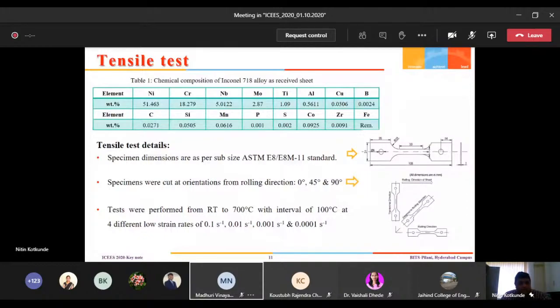It will take around 1 or 2 months of continuous dedicated effort to test the tensile material, because if you go to high temperature, the ductility will improve and the test will take more time. Let us say for Inconel material, the 0.0001 per second strain rate tensile test will take almost 22 to 24 hours for one specimen. So you can imagine we have tested around 110 tensile specimens to make sure of accurate and trustworthy material properties. And we have used our 2-zone split furnace